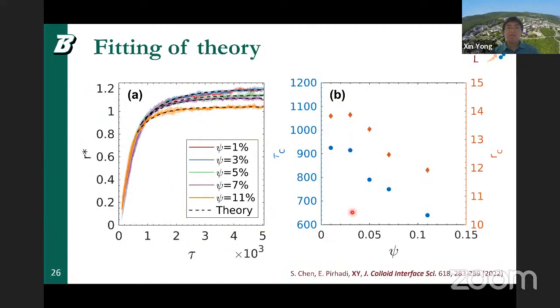So by fitting this system to our simulation data, we can obtain these characteristic quantities. As we can see here, as we increase the cross-linker density, we reduce the relaxation time, and this is because the polymer gets shorter, right? And so this trend is qualitatively consistent with the Rouse model. Of course, this is a network, so the real relaxation is much more complicated than the Rouse model, but the overall behavior is consistent.